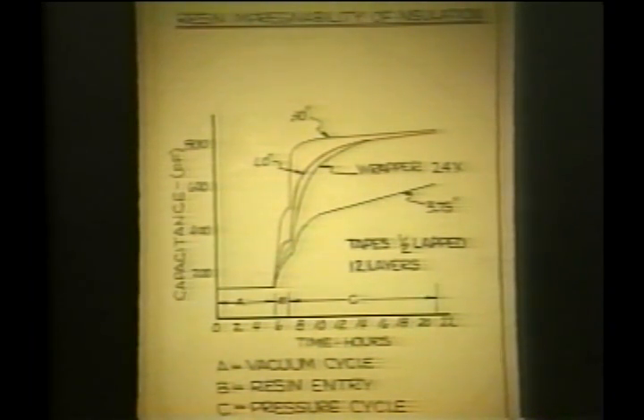Now, the interesting thing to note here is that the narrowest tape impregnates the fastest, as you can see, because it reaches its final capacitive level and then levels off in a fairly short period of time. The 1-inch wide tape, which is typically what we would use for insulating coils, is somewhat slower. And then, of course, the wrapper appears to be in about the same time frame as the 1-inch tape.